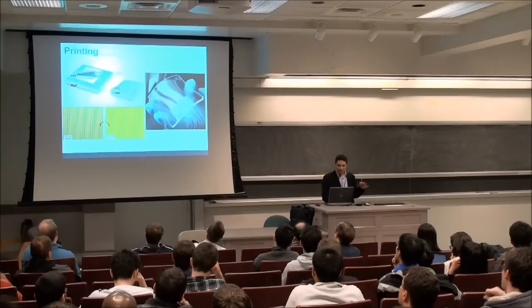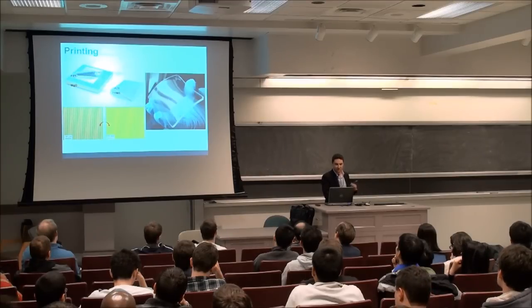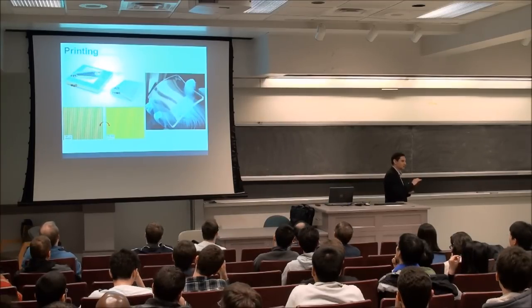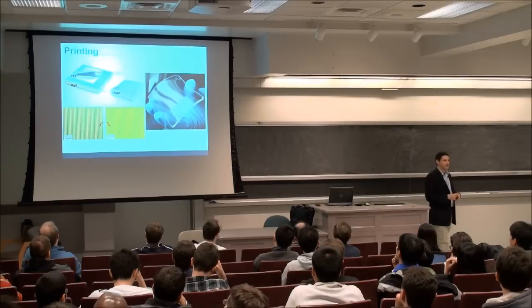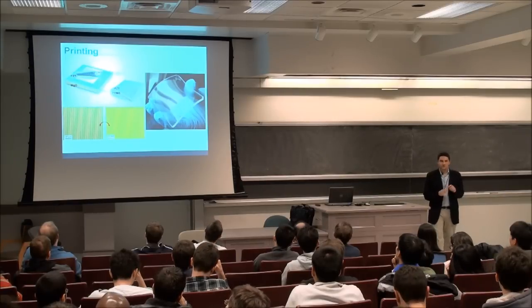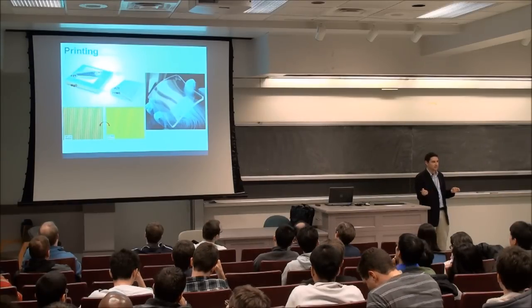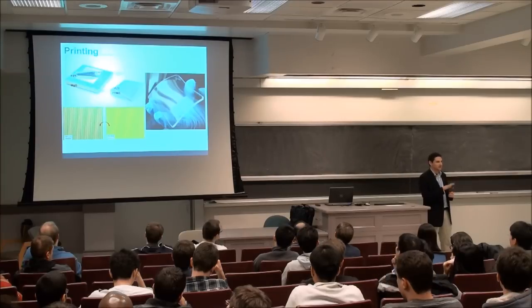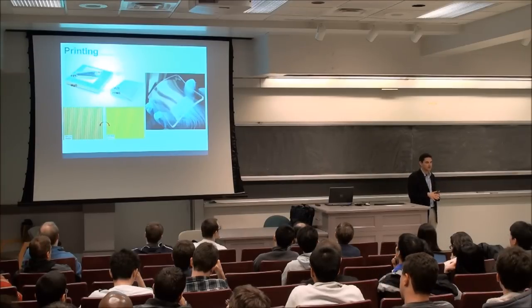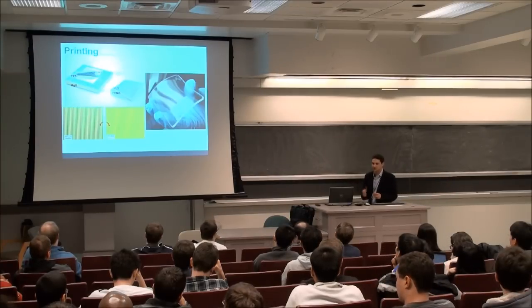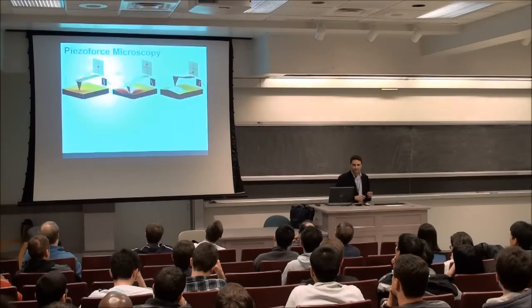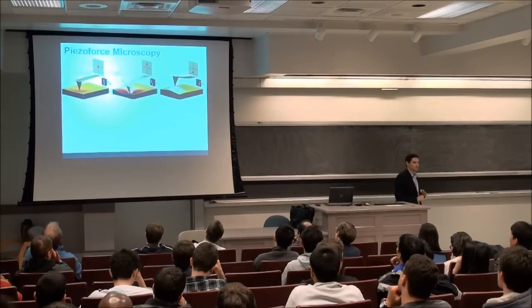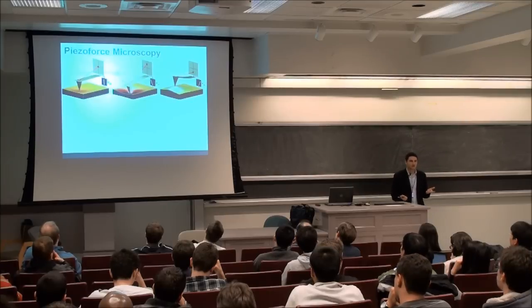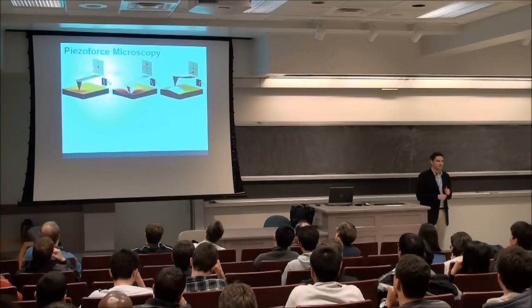So this is totally inspired by John Rogers' approach, this kind of transfer printing method. But now we have this PZT material on a biocompatible interface, right? And also the PZT here is very thin. It's nanometer, they're nanoribbons, and so that actually confers more flexibility to them than you would get in a bulk scale PZT, which is not very flexible at all. So the first question is, is the PZT still high performance when you transfer onto the ribbon?